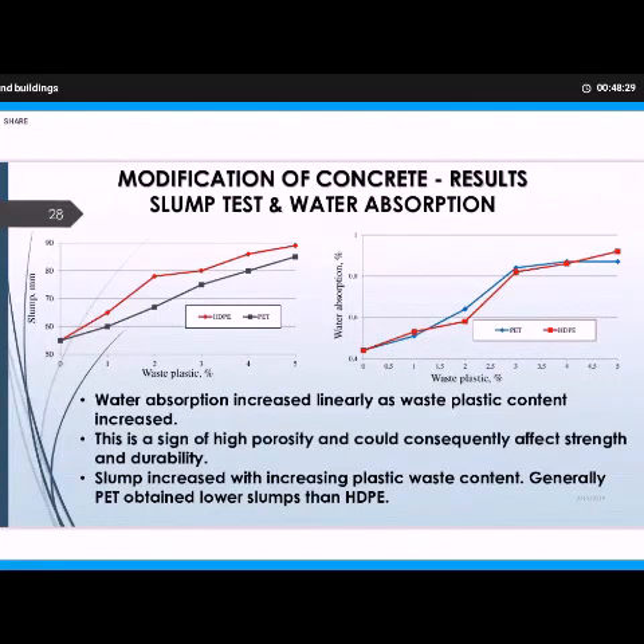So when you look at the graph, it is observed that as you increase the plastic waste content, water absorption also increased. And these are the indication of high porosity and thereby high permeability. But it must be stated that even though the water absorption increased, it was still below the maximum water absorption required, that is 1%. All the replacement levels had their water absorption less than 1%, which is a very good indication.